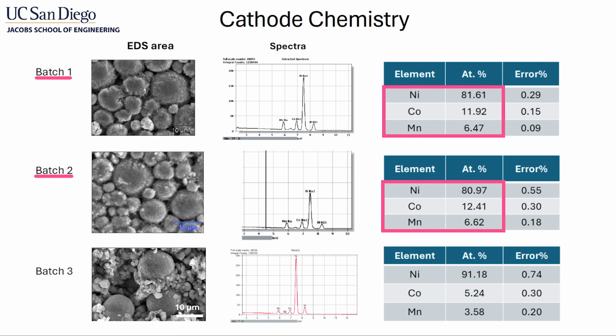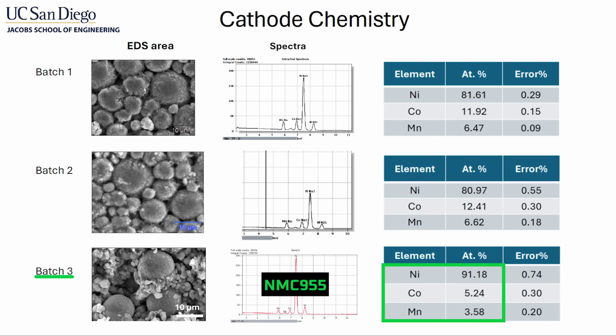The Generation 1 4680 cells were roughly the same in terms of composition: 81% nickel, 12% cobalt, and 7% manganese. This would be loosely classified as an NMC 811 cathode chemistry, corresponding to 80% nickel, 10% manganese, and 10% cobalt. The Generation 2 4680 cell is 91% nickel, 5% cobalt, and 4% manganese, which would be loosely classified as an NMC 955 chemistry, correlating to 90% nickel, 5% manganese, and 5% cobalt.